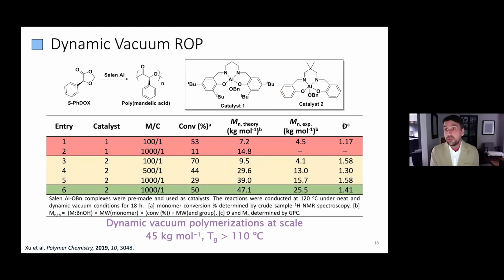Well, one of the things we do is do a lot of work on catalyst design. And I'm not showing you our stuff on organocatalysts, but on this polymerization system, if I simply switch from catalyst 1, which is a very traditional catalyst in ring opening polymerization, for one which is slightly less controlled but much faster, I now dramatically increase propagation rates as well as not changing the rate of my Tishchenko reaction. So competitively, I'm getting more polymerization versus Tishchenko. The other thing I do is I switch to a dynamic vacuum-based system, and I remove the formaldehyde as fast as I can. Unfortunately, we're not able to trap that out through other means. Vacuum has been the best in terms of our hands.